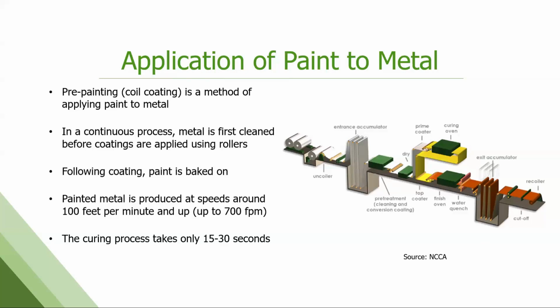The curing process, that is from the time the paint is applied to the strip until it is dried and fully cured, is 15 to 30 seconds. These are chemical reactions that are taking place. They are not air dried like house paints that we use. If you rolled some of this paint on a piece of metal and set it out in the sunlight, years from now it would still be wet. It would never actually dry. So very different chemistry.